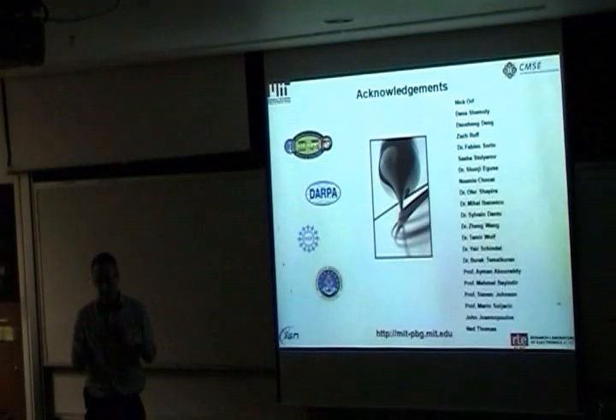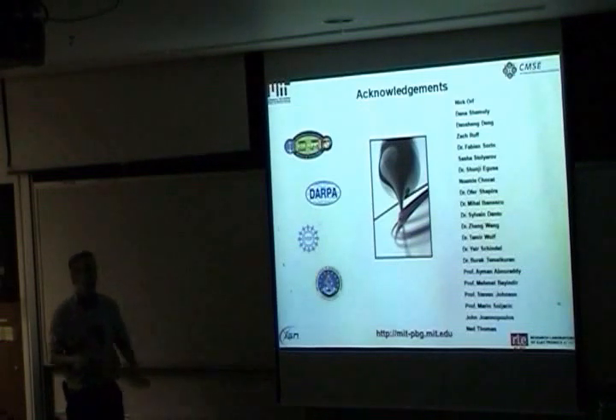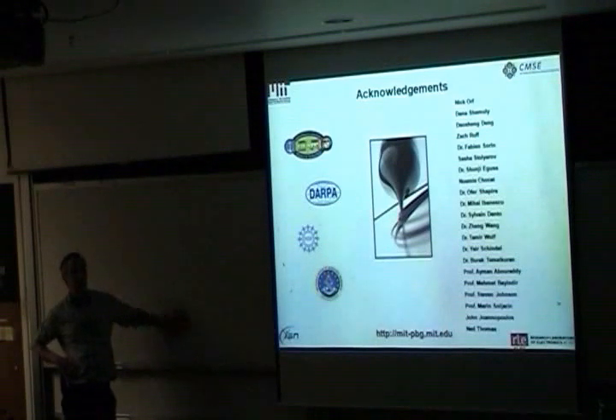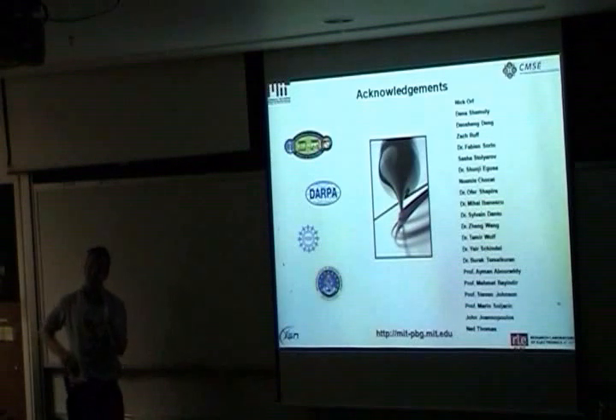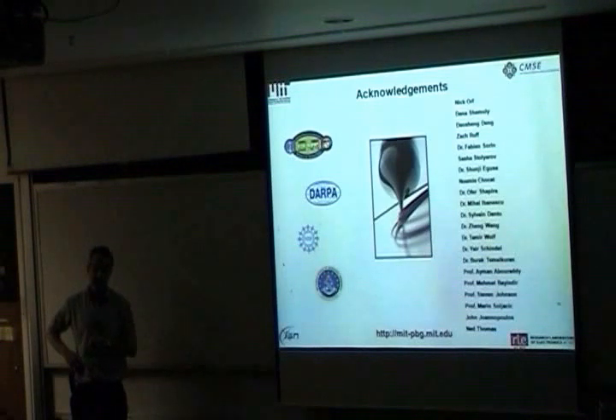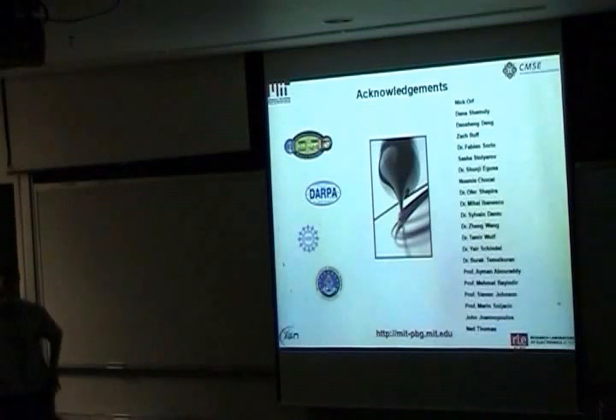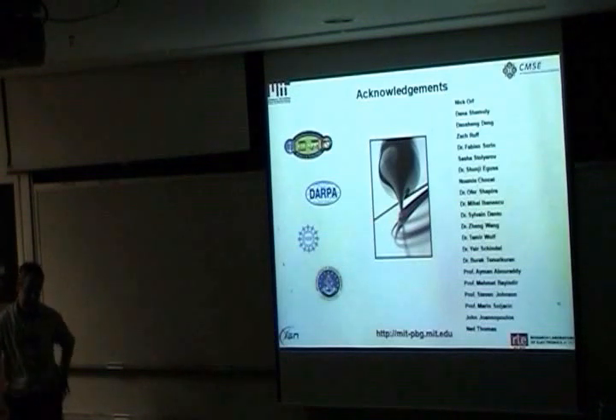Now, it is a composite, and you do have rigid elements going through. So once you dig into the next layer of trying to answer this question, there's a whole bunch of questions that have to do with mechanical strength. But we're drawing these, and let me give you an example. The tension that we typically apply, even in the draw, is on the order of a kilogram. The cross-section of a fiber is probably a few hundred microns, and that's when it's in the fluid state. So you actually get fairly high stresses developing, and that's the reason you could realize these intricate structures, because you really are using the stress fields and viscosities to negate surface tension.